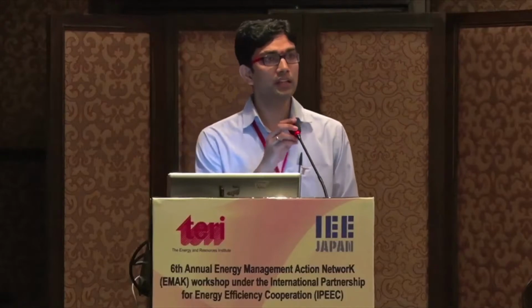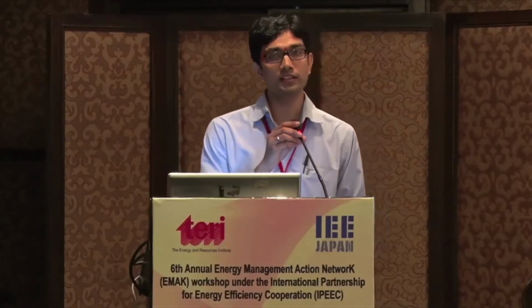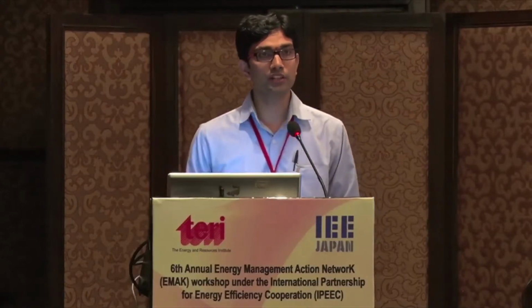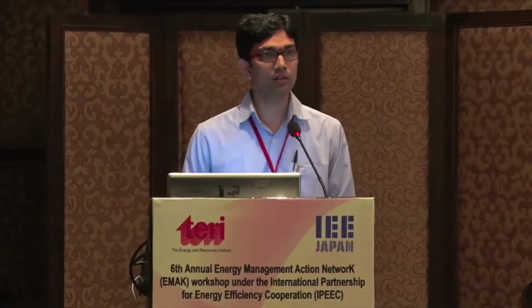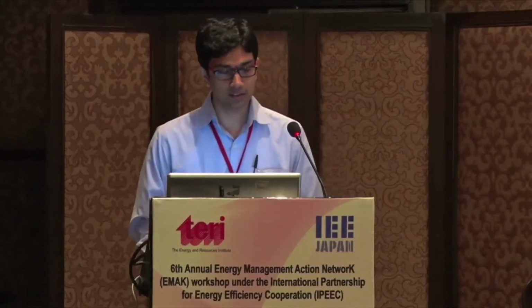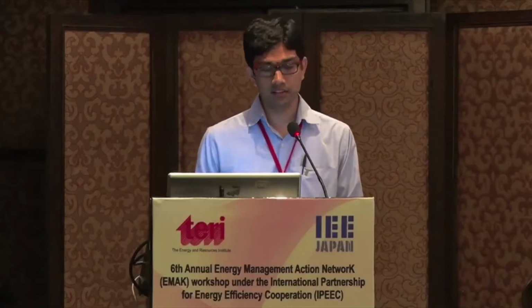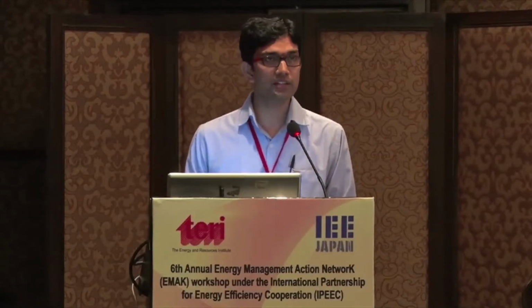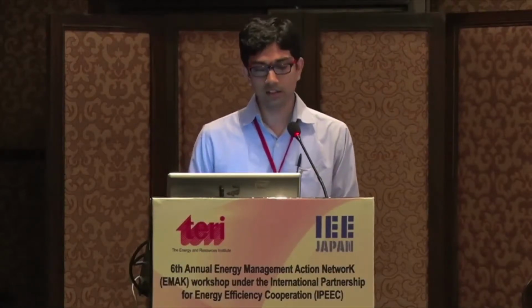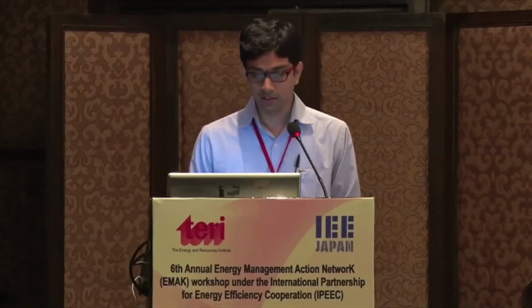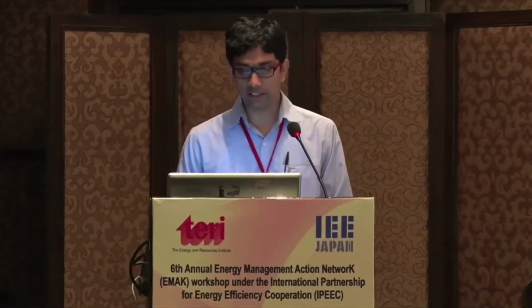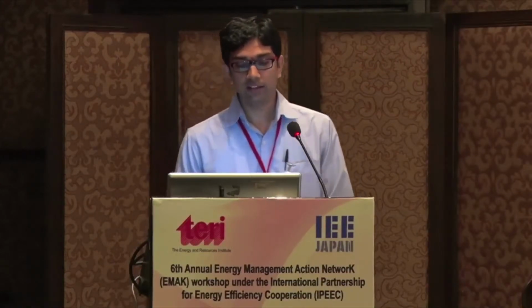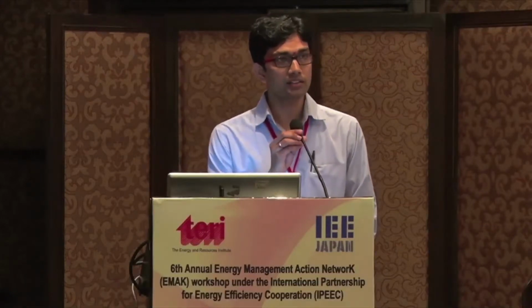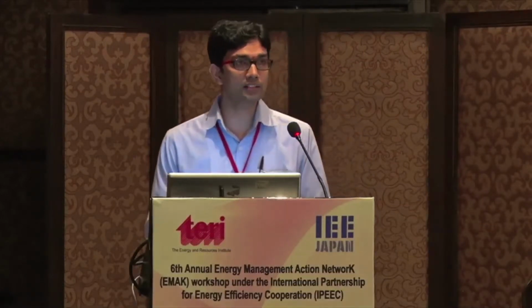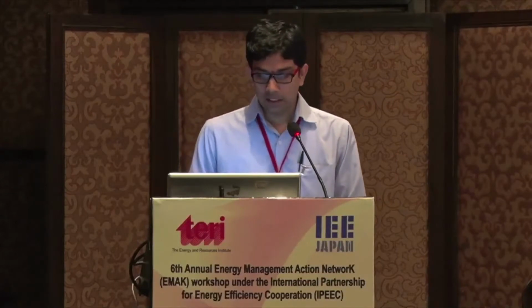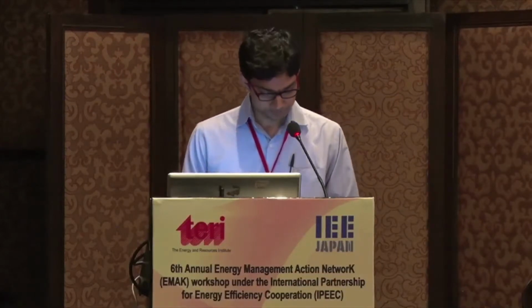If you look at the typical efficiencies of a forging furnace, we have had opportunities to work on more than 30 odd forging furnaces in Faridabad. And again, talking about the PNG furnaces, we have found that on average, the efficiency of the furnaces is around 33%. On the right side of the Sankey diagram, you would find that the major loss is happening on account of dry flue gas loss, followed by other reasons.